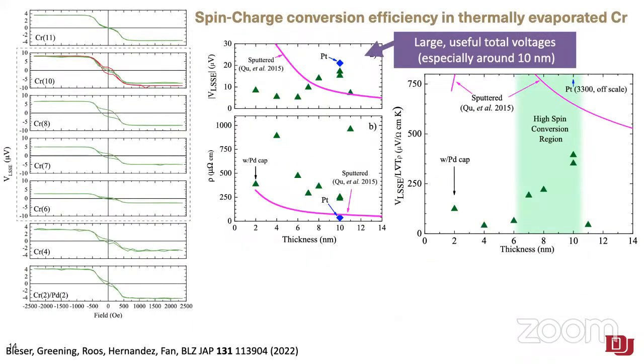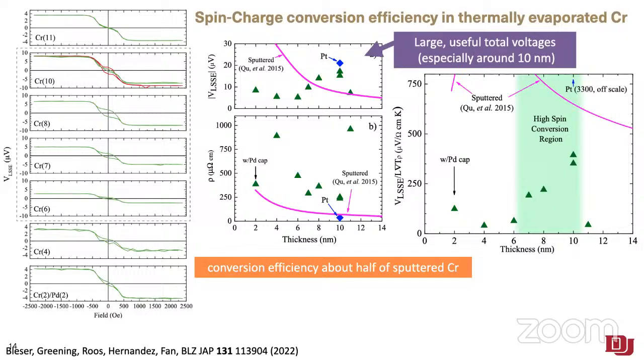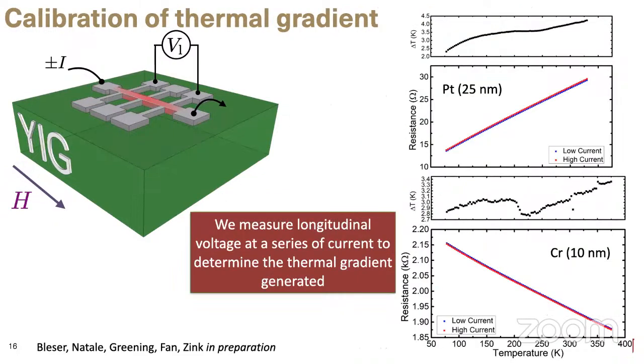You mentioned you measure the longitudinal resistivity of your whole bar as a kind of thermometer, but I wonder, isn't it better to just place an actual thermometer on the surface of the YIG, because your temperature gradient is penetrating your sample, right? Then basically, I think the bottom part of your sample is at the same temperature as your environment, and your top layer is being heated by the current. So why don't we just place a thermometer chip on the surface?